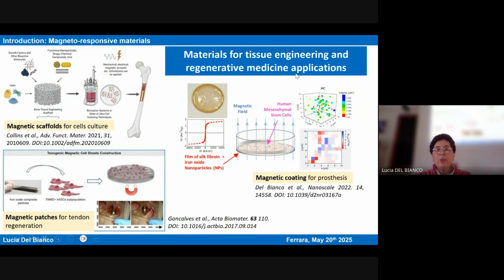And another field of application is that of regenerative medicine, for instance, for the creation of scaffolds or patches, which essentially are supports for the culture of cells, both in vitro or in vivo. You can build materials that are inserted in our body to develop new tissue. And it has been found out that if you put nanoparticles in these materials and apply a magnetic field, the cells grow and proliferate in a better way, and also differentiate very fast in the case of stem cells. This is a work we have carried out together with Federico and other collaborators.